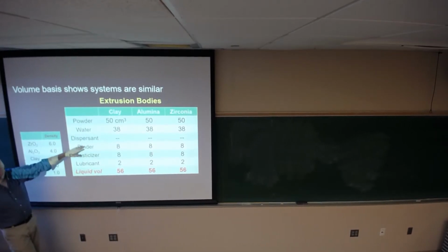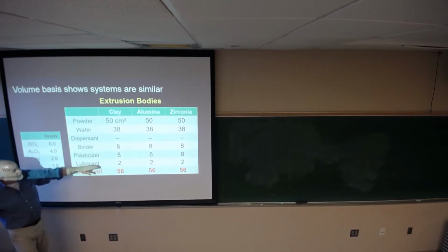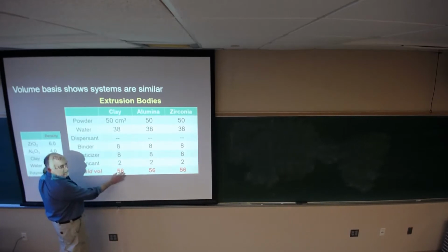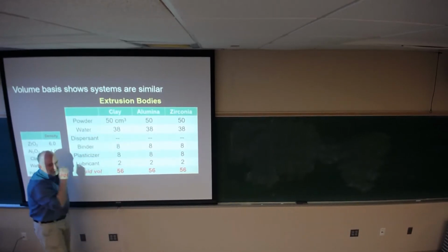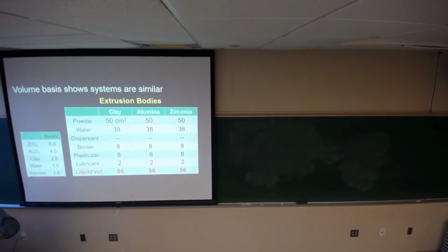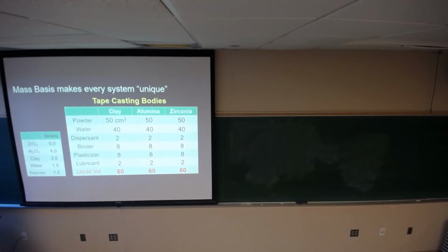So if I bring in binder, I have 8% binder in the system on a volume basis. Okay, when I get done, I end up with 56%, versus 50. So I have 6% excess liquid in the system. We could argue that the clay case may not be entirely correct because clays generate that excess volume automatically. I'm going to talk about that soon. Take the next one, the same thing. Now I'm at 60%, so I have 10% excess in the system.